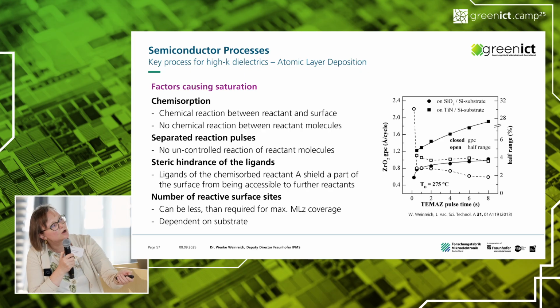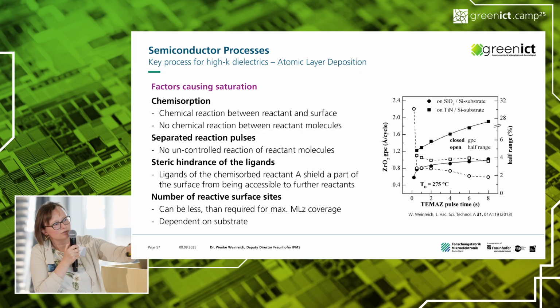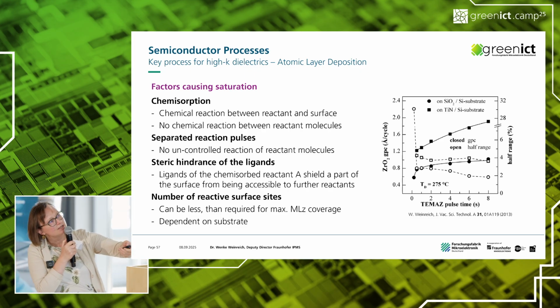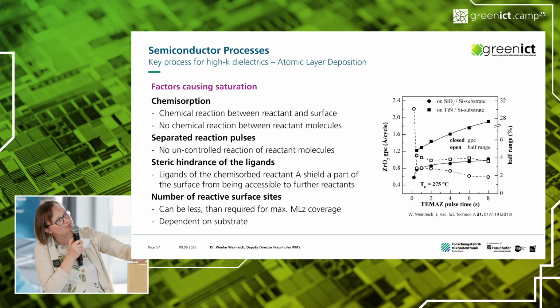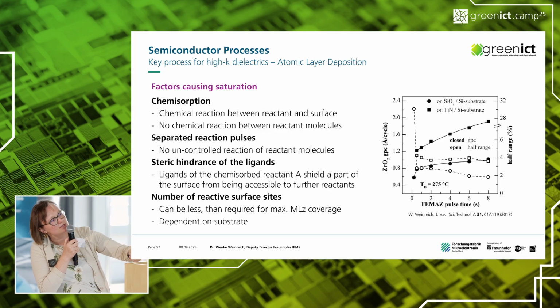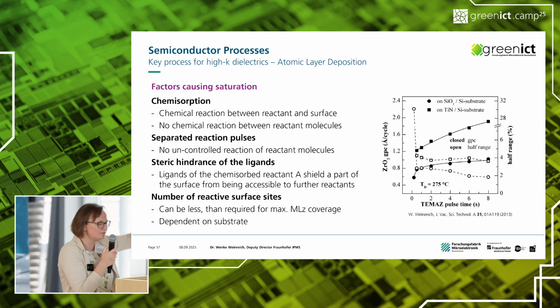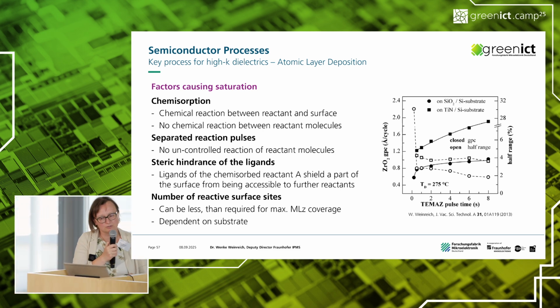It doesn't matter how long you have material inside the chamber, the growth rate is not increasing. You only have one small layer on top. But here you can see that this can differ if you have a different substrate. This is the line for silicon oxide. This is the line for titanium nitride, which is a rougher material, higher surface area, so you can deposit more material.